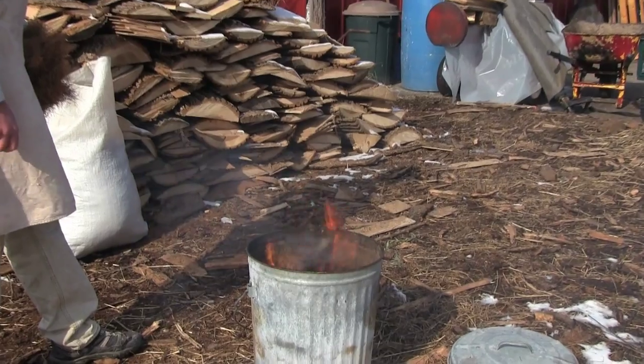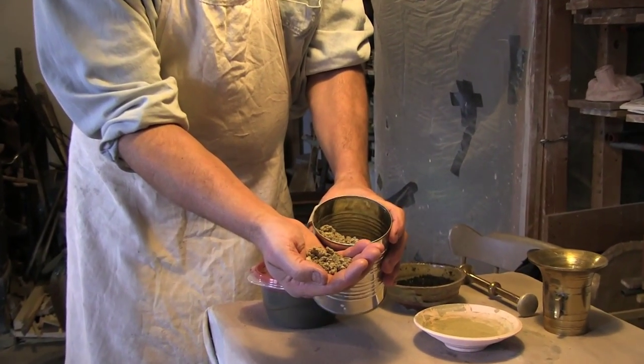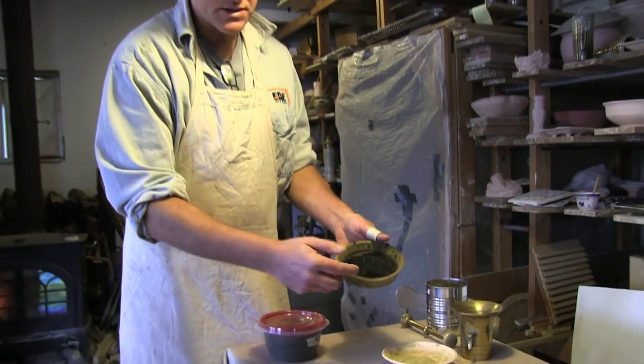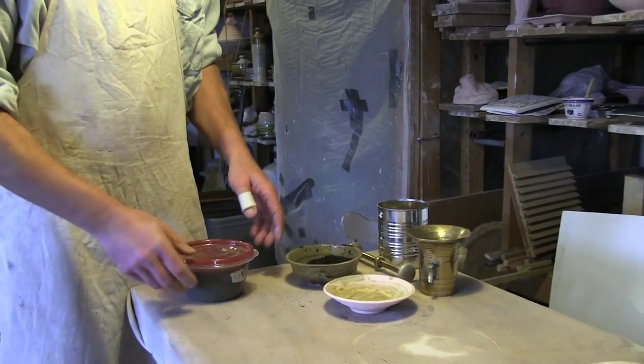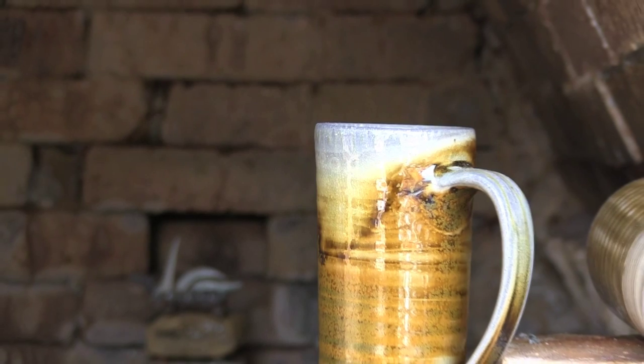Today I just picked up from Bloxham Company 80 pounds of cork, and I'm actually going to burn that, collect it as ash, and then what I do is take that dry ash and screen it. Here's some of the local clay I'm digging out from our property — I basically just crush it, get it pretty dry, and screen it so it's more powdery. This is the cork we just saw burning, and the test I ran for this particular load was a 50-50 of equal parts of each. With water added, this needs to be the consistency of thick milk so it can go on to the pots.